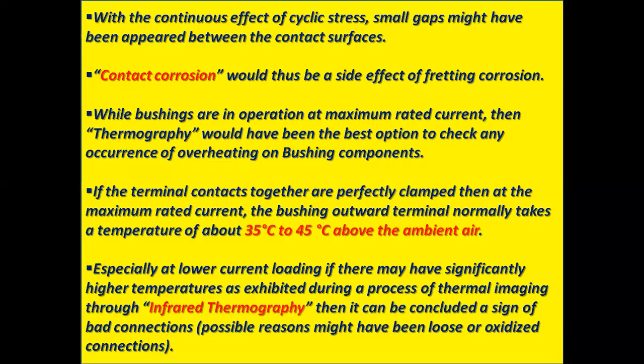While bushings are in operation at maximum rated current, thermography would be the best option to check for the occurrence of overheating on bushing components. If the terminal contacts are perfectly clamped, then at the maximum rated current, the bushing outward terminal normally reaches a temperature of about 35 to 45 degrees centigrade above the ambient air.